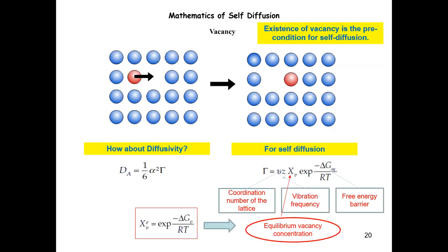Vacancies are equilibrium defects in the sense that, if you increase temperature, they increase. If you keep the temperature there forever, they're still going to stay there forever. They're not going to decrease in number, or be gone, right? So we know as a fact they're equilibrium defects in this sense. But the question is why? If you introduce one, you have to do work to the system to increase the energy. What is the gain by introducing a vacancy?